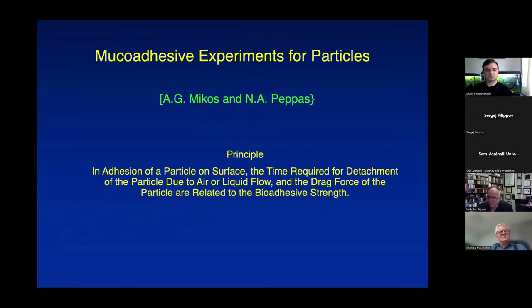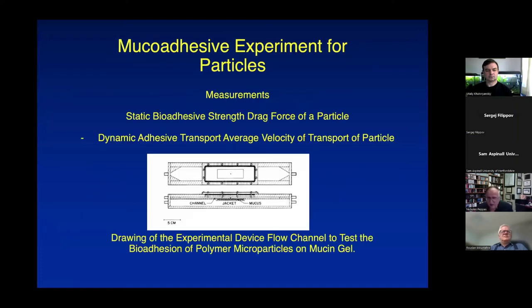But with Mikos, much later, we did an experiment that was totally different. We took particles and we put them in a special channel that we made in the laboratory from plexiglass, and it was covered on the top. And here we would take the mucus of an animal and put it there. And you would put one particle or two particles, and we had a microscope on top.